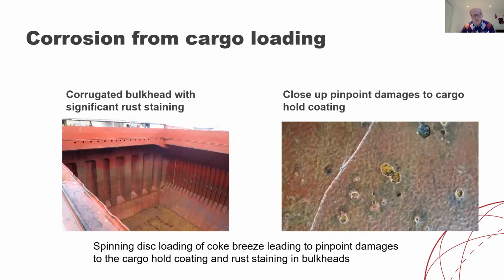And the last example here is corrosion from cargo loading. I managed this spinning disc loading of coke breeze, where you can see here on the right hand side you get these pinpoint damages from the coke breeze penetrating the coating and making damages. And then the overview picture on the left hand side is showing significant rust staining from all these pinpoint damages into the corrugated bulkhead.